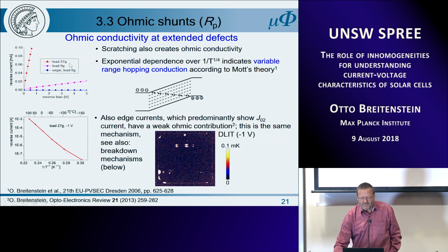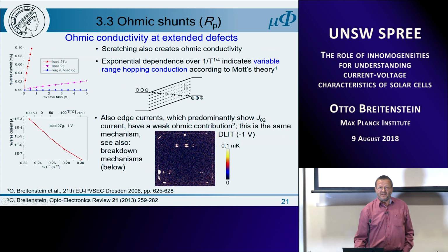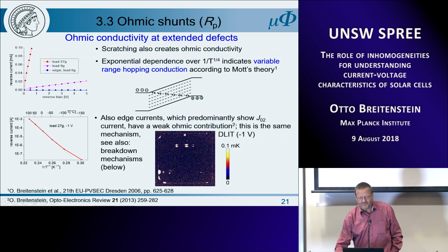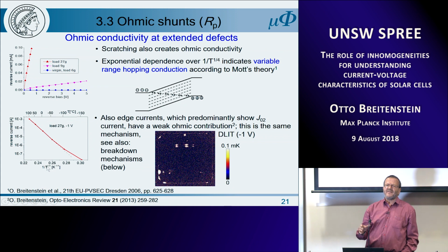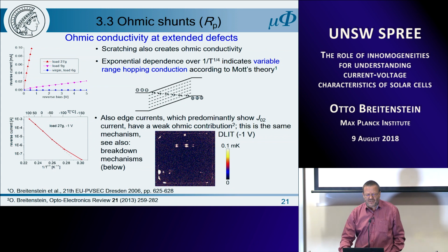And this is hopping conductivity, and this was proven by measuring the temperature dependence of this reverse bias here, and that's our model. So we believe that we generate a number of defects across the whole energy gap, and then they are so close that they interact with each other, they overlap and lead to this hopping conduction. And this is proven here by this logarithm of the reverse current over 1 over T to the power of 1/4. That's a very special temperature dependence, and it is predicted by Mott's theory for other systems. But this special temperature dependence is only expected for this kind of hopping conduction.